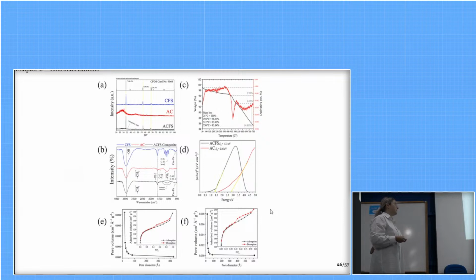FTIR analysis. The surface area of the activated carbon decreased after we added the chalcopyrite nanoparticles. And most interestingly, we observed its high stability up to 750 degrees during the thermogravimetric analysis, with a decrease of only 15% of the mass of the catalyst during this increase in temperature. And the band gap decreased from 2.86 electron volt to 1.33 electron volt for the catalyst, showing an enhancement in electronic properties.